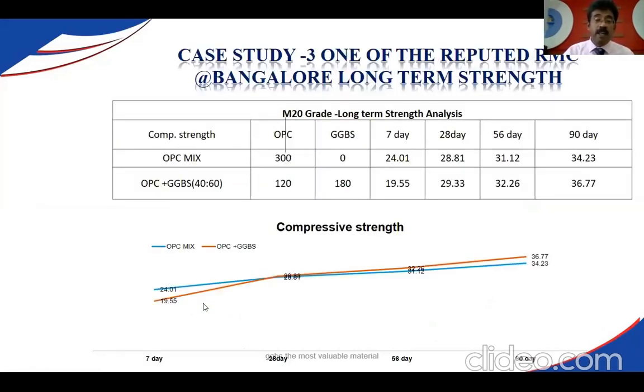So a couple of case studies I want to show. We have studied the long-term strength using almost 40% cement, 60% GGBS for M20 grade of concrete. We have done a study up to 90 days, casting more than 500 cubes. So we can see the gradual improvement in the compressive strength. It gives lesser 7 days strength, but 28 days is much better, because we measure the concrete strength by 28 days. At 56 days and 90 days, the strength is much better compared to your OPC control mix.